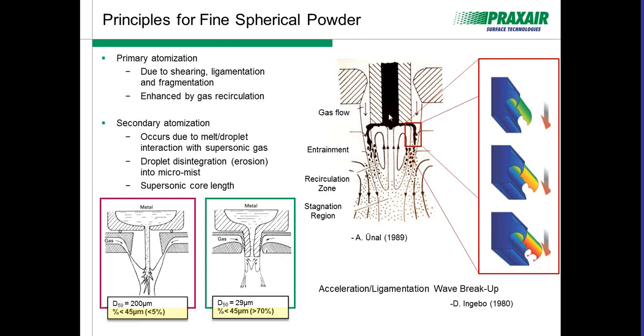When we go back to the schematic up here that was published by Ünal back in 1989, it really shows that as the liquid interacts with the gas structure, you can create a recirculation zone. And this is due to the high pressure gas zone that lies below the Mach disk. I'll show a schematic of that on the next page to better clarify what that means. But in general, the liquid is forced across what we call the landing of the nozzle. It has been sheared by this high velocity gas and broken into these primary droplets.